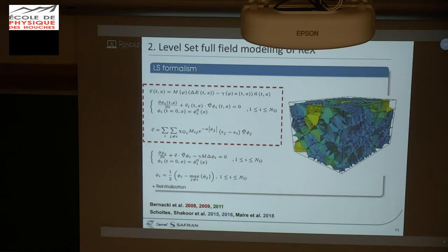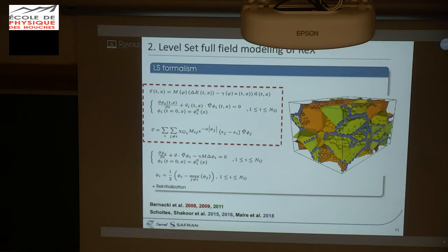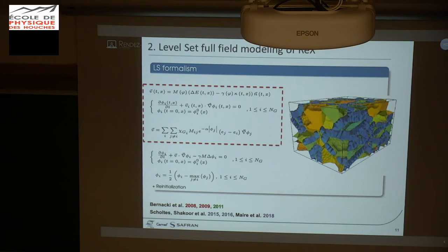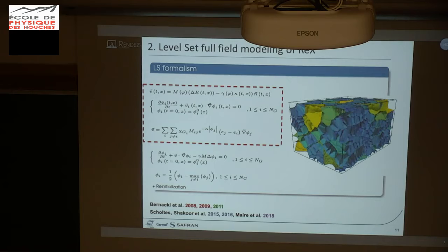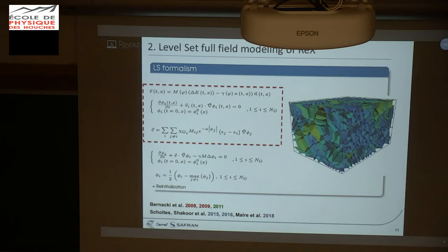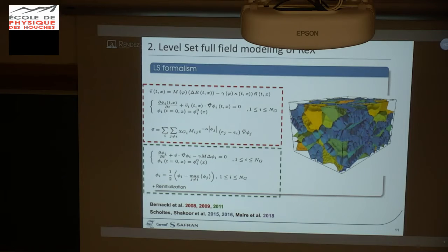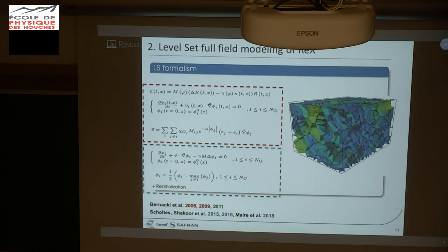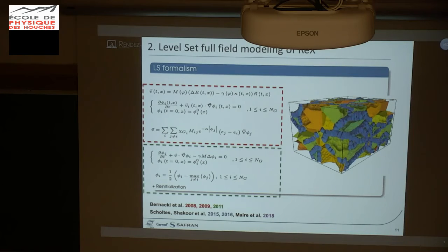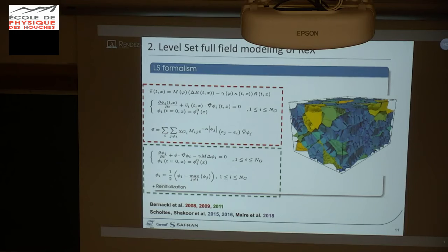In fact, with the level set formulation, you can simulate this kind of evolution with a classical convection equation used for the level set evolution. And 10 years ago, we added a diffusive term in our equation to take into account grain growth by capillarity. Finally, with this formalism, we are able to simulate static or post-dynamic evolution or grain growth by considering the two driving pressures that I have shown you before.